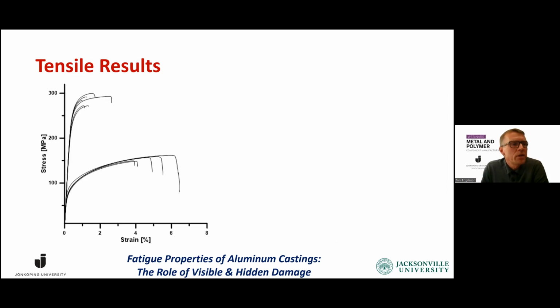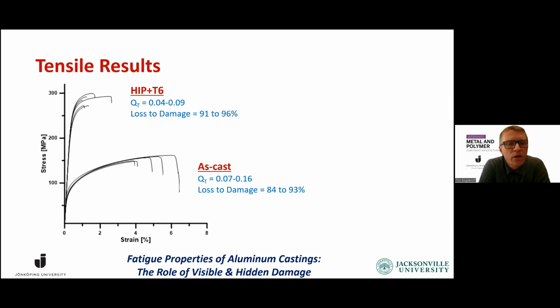Then we do the tensile test, just to validate what the properties are. So we have the as-cast that has up to 6% elongation. We have a quality index of this one between 0.07 to 0.16. So it's a loss to damage between 84 to 93%, depending on that. And that is a lot of porosity in this one. But one of the interesting parts is when we apply HIP and T6 and we look at the same properties, the loss to damage is 91 to 96%. So we are closing the pores, we make the material stronger, we get the matrix stronger, and we actually, in this case, open up more defects in the material when we apply tensile stress.